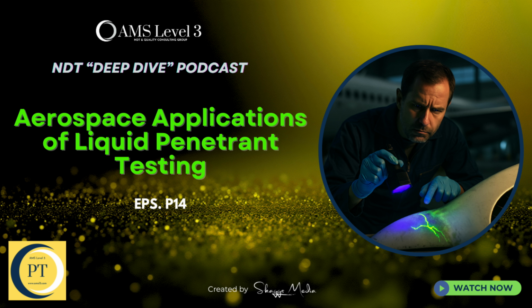And what's that limit, usually? Typically around 70 degrees Celsius or 160 degrees Fahrenheit. And the reason is, if you get it too hot, you can literally damage or quench the fluorescent properties of the dye that's trapped in a crack. So the defect becomes invisible. It becomes invisible. The equipment is controlled to protect the chemistry. It sounds like the entire system just requires this constant, redundant verification. The NDT lab is basically one continuous audit trail.